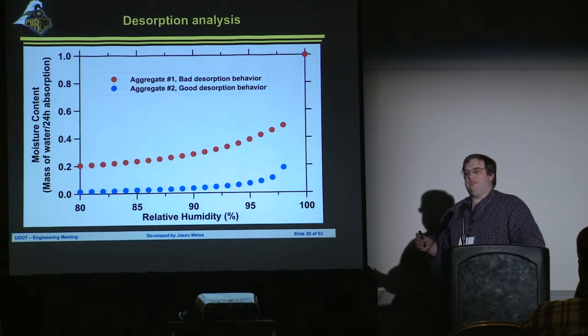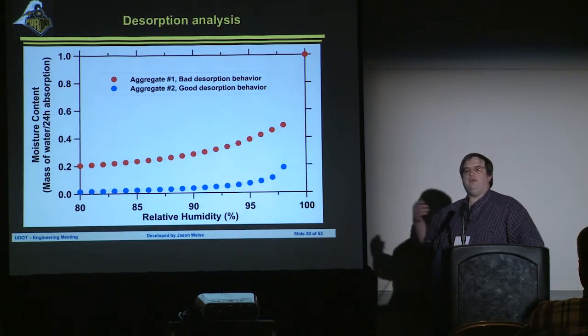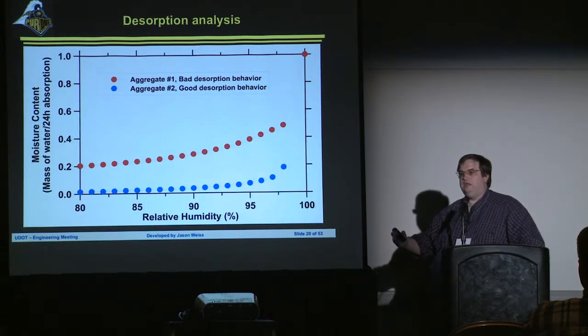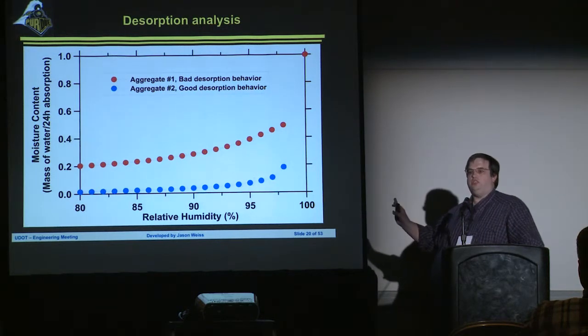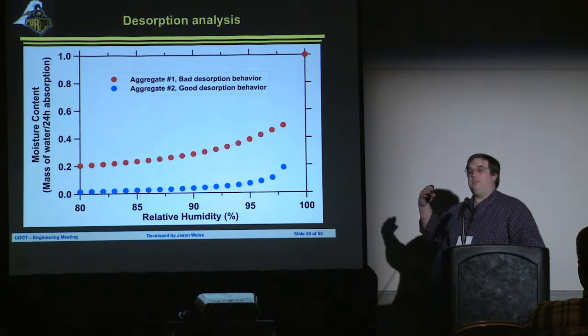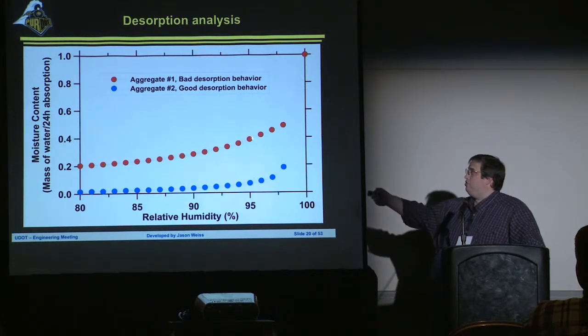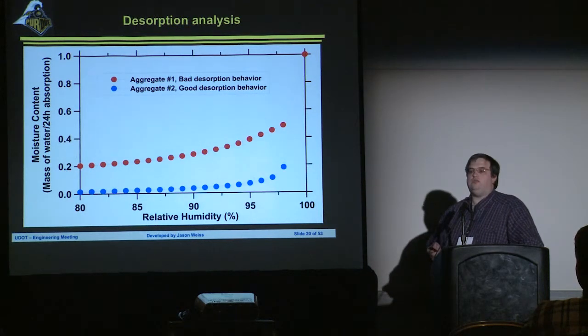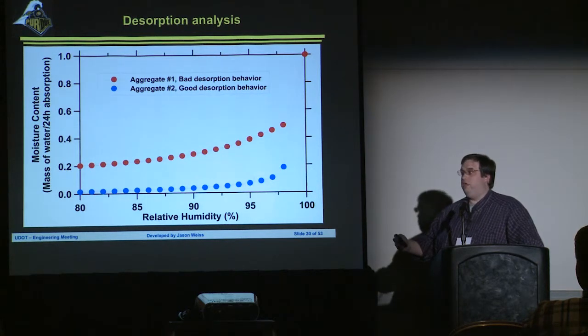So what does this mean? This means that they have pore sizes that are bigger than what we see inside the paste, so they readily give up their water when it's needed. This is exactly how you would engineer a system to get the optimal type of performance that you would want. So you're getting the most efficiency. Does that mean you couldn't use this aggregate to get internal curing? No, you could use it. You would just need to use more of it than you would see with a conventional lightweight aggregate.